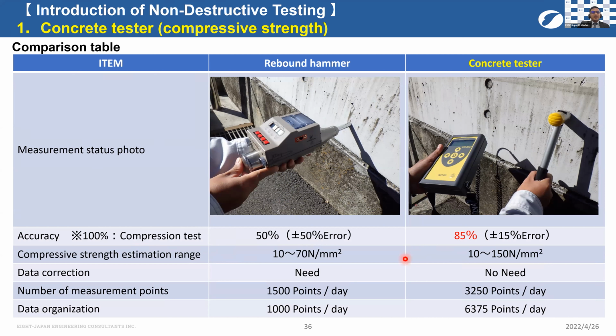The compressive strength estimation range for rebound hammer is just from 10 Newton per mm square to 70 Newton per mm square. That is why it is difficult to be used to test compressive strength of high strength concrete. The estimation range for concrete tester is 10 to 150 Newton per mm square. So it can be used for high strength concrete testing also.